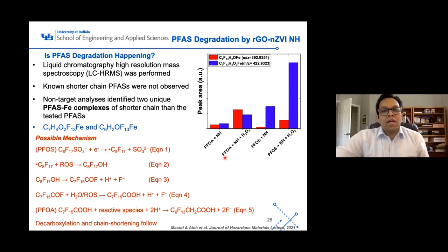But the question is, we are seeing oxidation, but is the degradation really happening? So what we tried to do is we did high resolution mass spectroscopy to identify different unknown products. What we have found is that they have not reduced to very small carbon or carbon hydrogen structures, but they have reduced. So we have a C7 and C6, like one and two carbon reduction. We have seen also fluorine reduction. So we are seeing carbon decarboxylation and partial defluorination in this process by oxidation.